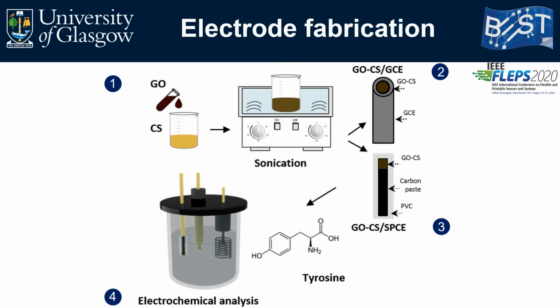The graphene oxide Chitosan modified carbon electrodes were fabricated by successfully immobilizing a homogeneous graphene oxide Chitosan film at the surface of the glassy carbon electrode, which measured 3 mm in diameter, and at the surface of the screen-printed carbon electrode, which measured 1 cm in length and 3 mm in width, following a simple ultrasound-assisted chemical reaction strategy.